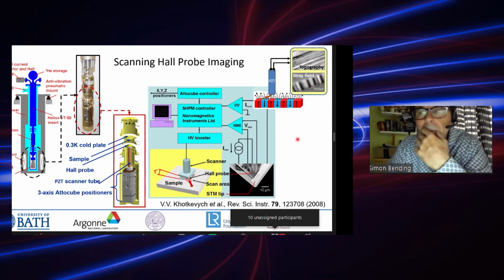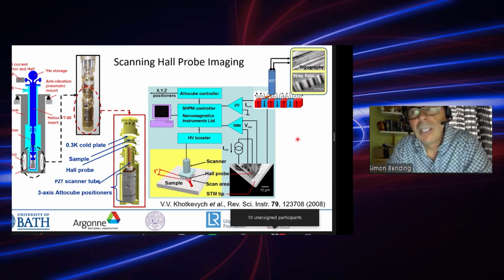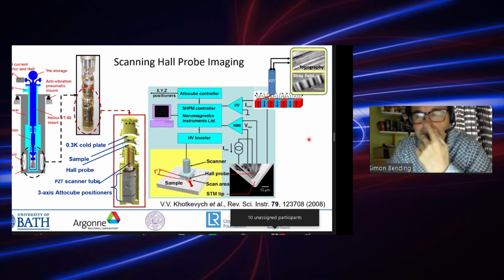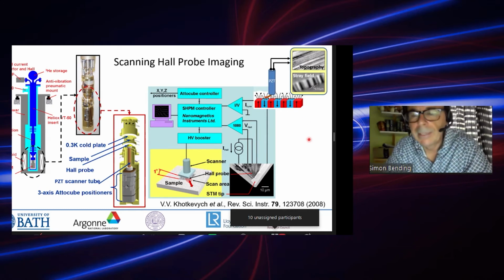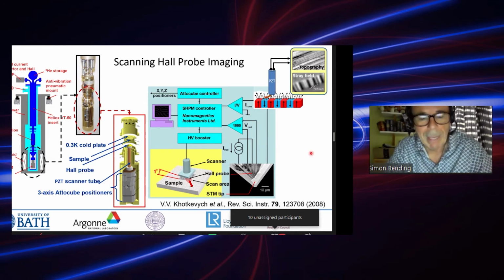But in the case here that we're dealing with, there is no real topographic structure on our surfaces. They're atomically perfect and atomically flat. So there's very little point in actually mapping the surface topography, and that takes a lot of time anyway. So we typically back off a few hundred nanometers and then scan the surface very rapidly in what we call flying mode and just record the magnetic data.